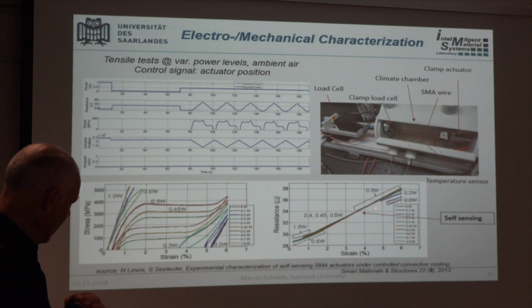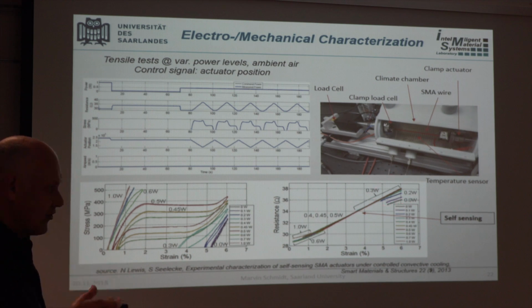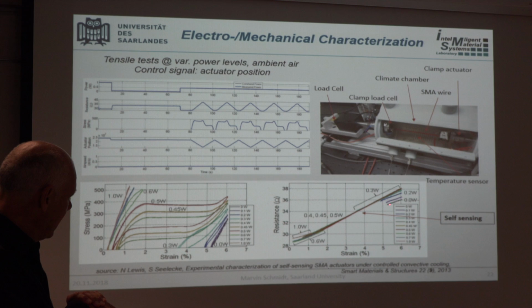So when we start here, this is the change in electrical resistance during this experiment at 0 watts. So this is stretching a martensitic wire and unloading it. And what you see is the simple geometric change in the resistance of the wire. So basically it's a strain gauge effect that you have, right? Then I apply 100 milliwatts and I repeat the same experiment. You hardly see a difference here on the mechanical side, but the resistance jumps up by a notch and undergoes almost the same range, and the jump is due to the temperature dependence of the resistance.